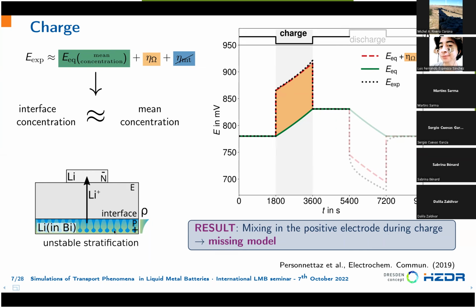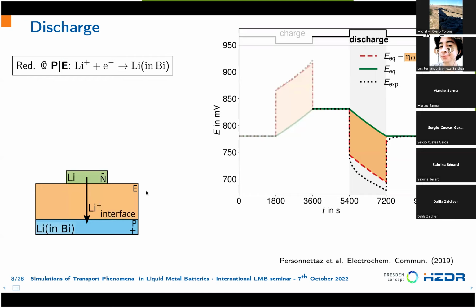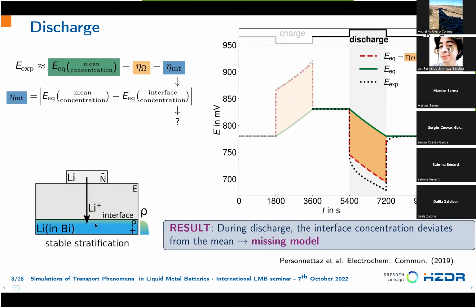And this mixing can be explained by the fact that we are removing the light fluid from the top of a heavy fluid. We locally generate heavy parcels of fluid that then sink down and generate a strong flow that mixes everything very well. During discharge, we have the opposite reaction. So we are depositing light lithium on top of the heavy alloy. This is a stable condition because we are depositing the light over heavy.